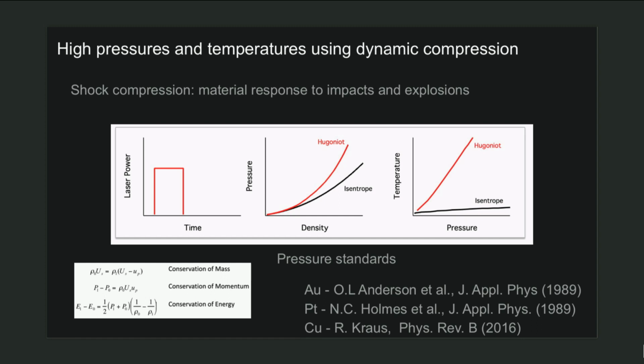When we think dynamic compression, the first thing that comes to mind, of course, is shock compression. Shock compression can be defined as the material response to impacts and explosions. And so, again, we send pressure waves through the sample, and the rise time of a shock wave is dependent on the material properties, and that's on the order of picoseconds. But the pressure-density path that it follows is set by the fact that they follow a higher temperature path. And so one difficulty with dynamic compression for a long time was the fact that only shock compression was achievable. And so all of the interesting materials that are of interest to our planetary interiors, for example, all melt at too low of a pressure to be relevant to super Earths and exoplanets.